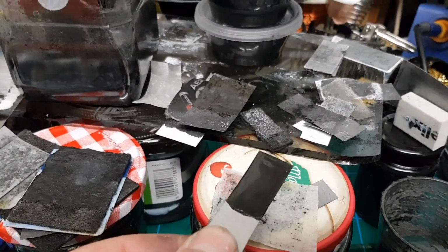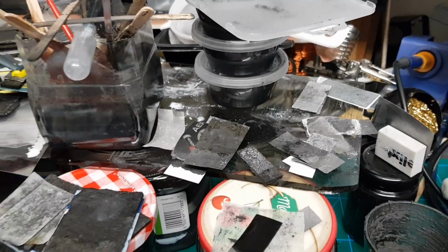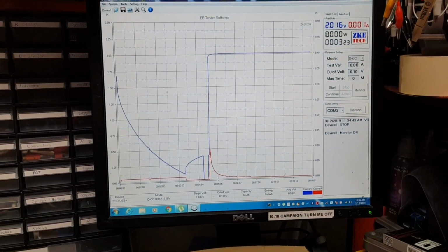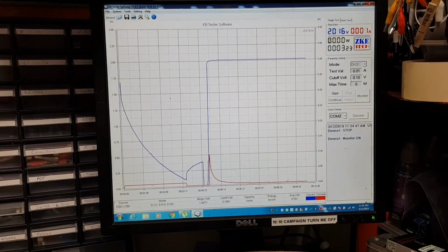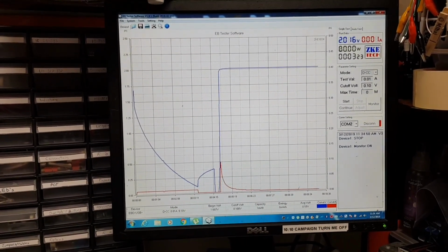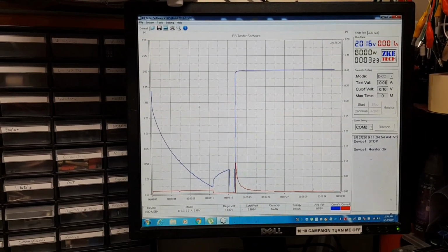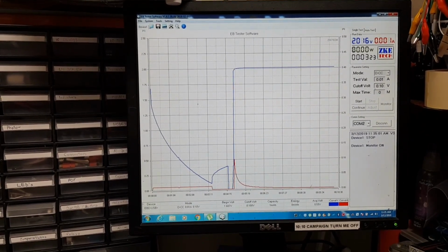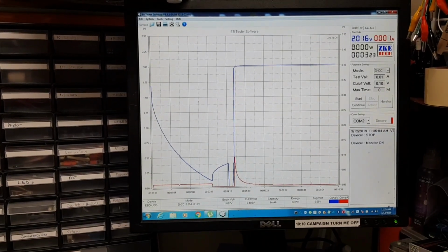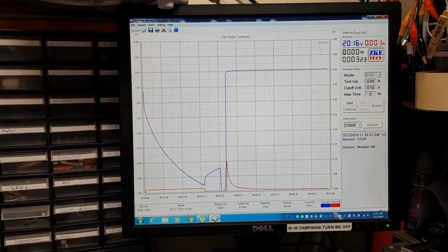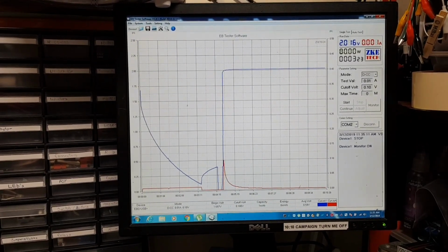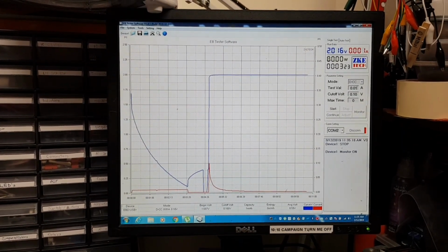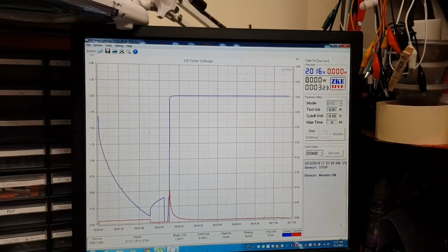At the same time, I'm also building another one which is even smaller. I'm painting it straight on the graphoil. Still drying the first layer. I'll try to put a few layers, instead of letting it dry on a piece of glass and then peel it off. I've noticed that when you put the blade under the carbon, it will make it crack a little bit, and maybe that is affecting the performance. So I'll just keep it straight on the graphoil exactly as it will dry, then we will start testing it. And yeah, I'll be back later.